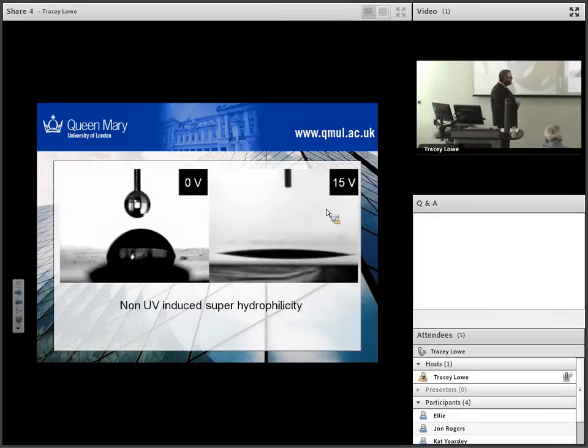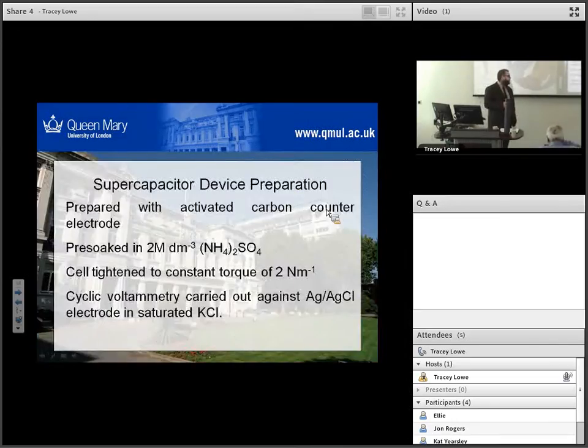But nonetheless, one of the things we can do with these two samples is get non-UV induced superhydrophilicity. This is really important for supercapacitors because we're essentially looking at the accumulation of charge in the Helmholtz layer, and better wetting with your electrolyte means you can have more of this, so you get higher capacity. This is one of the reasons we think these work reasonably well.